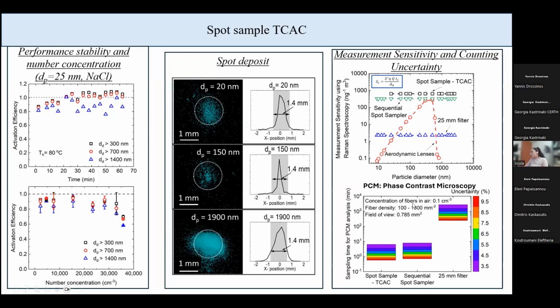So if we assume a concentration of fibers in the air of 0.1 fibers per cubic centimeter, I was able to calculate the sampling time that was required when we used the spot sampling TCAC in comparison to the sequential spot sampler or the 25 millimeter filter. We see that we can get way lower sampling times compared to the 25 mm filter, and slightly lower compared to the sequential spot sampler.